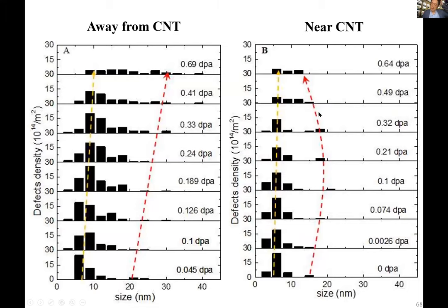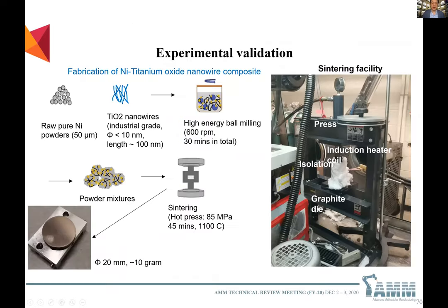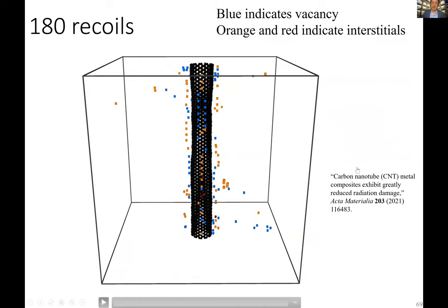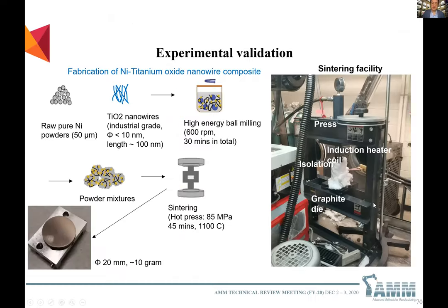And we have done quite a bit of statistics. It turns out that for radiation damage, what matters is not the average radiation defect size. What matters is the extreme value statistics: what's the biggest defect cluster that you can find? In this sense, having this one-dimensional nano dispersion limits the biggest defect size, and we think that's the key reason for the improved radiation tolerance. Like I said, the previous material forms this aluminum carbide, which is not very radiation resistant. But we have now found other nanowires like titanium oxide nanowires, and we have dispersed them in nickel alloys.